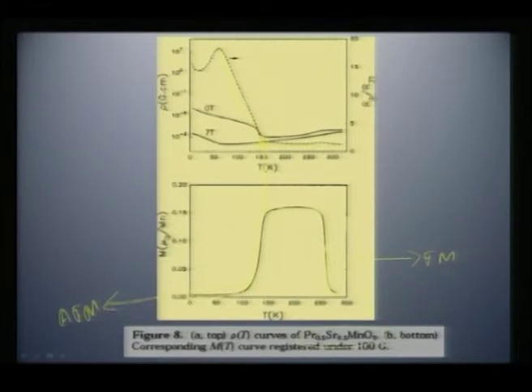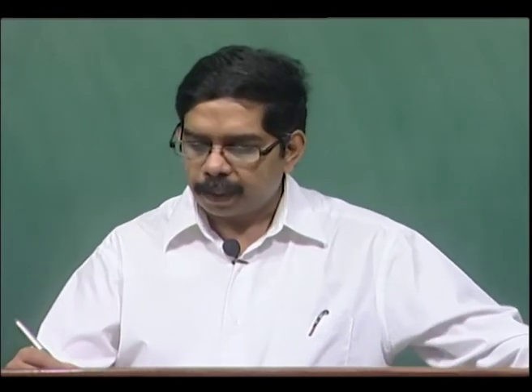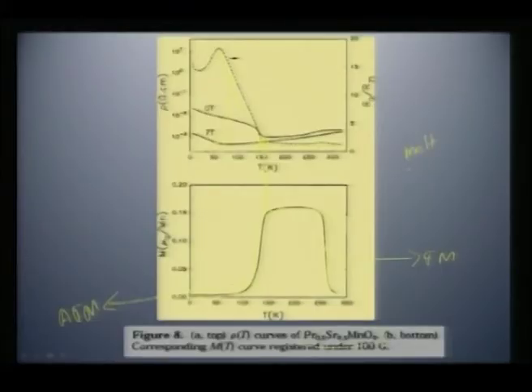If you try to apply a magnetic field, you can see immediately you can melt down this insulating phase to a metallic phase if you apply 7 Tesla, a very high magnetic field. In other words, you can melt the charge ordering mainly using magnetic field. Okay. There are other reports where you can melt this charge ordering by applying very high pressure.